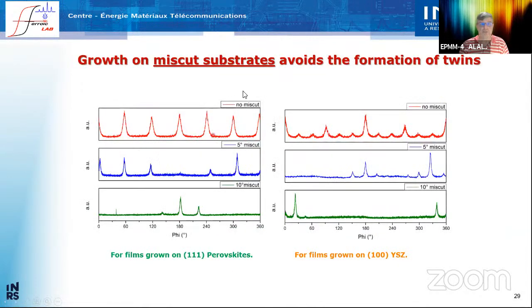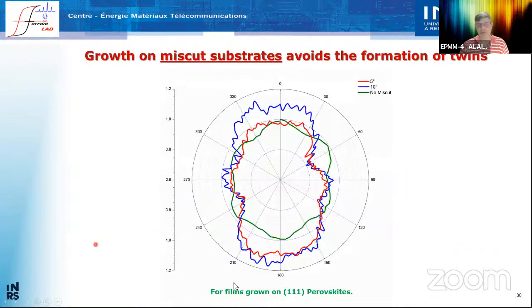So what we did is we tried to use miscut substrate. You see here the substrate, the miscut angle is increasing. And by doing that, you can select one of these orientations. And indeed, the magnetic properties now are again oriented along only one direction, as you can see here.